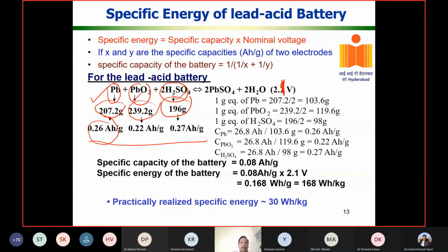Okay, and then you calculate the specific capacity as 1 by x plus 1 by y plus 1 by z. So many people don't consider sulfuric acid, and in lithium ion cell we don't consider the electrolyte. Actually we consider only cathodes and anodes, and we calculate the specific capacity of the cathode itself if it's a half cell. Okay, so here it's both. Sulfuric acid takes part in the electrochemical reaction, so we consider this, and if you don't consider it, you get a different number, and I'll tell you that. So you got the specific capacity, which is 0.08 ampere hour per gram.